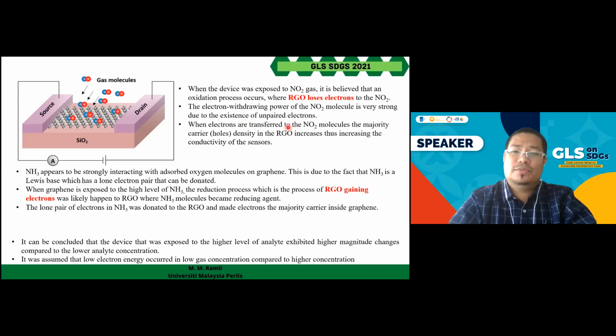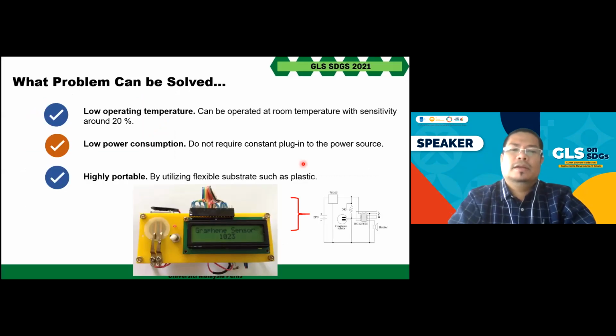So basically, when you expose it to the nitrogen dioxide, your RGO tends to lose electrons to the nitrogen dioxide. And then the resistance becomes lower, because we believe, based on the literature, that our reduced graphene oxide is a p-type material. So when it loses electrons, the majority carriers are holes. That's the reason why your resistance becomes lower and the conductivity increases.